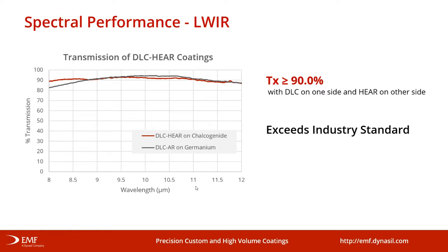As far as transmission, we typically are at 90% throughout the entire wavelength range. Here you can see two curves, one for germanium and one for chalcogenide. This includes both the DLC and AR coating, as well as the material transmissiveness.